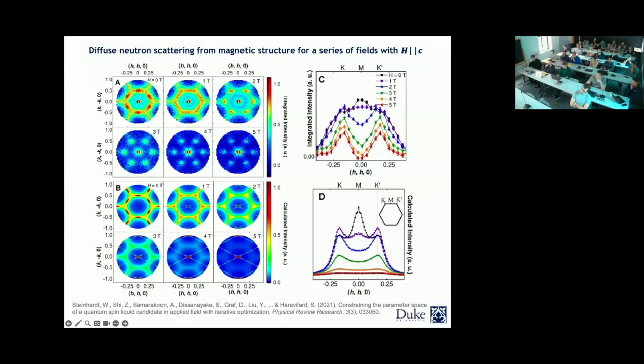Okay. So what we did was that we went up in the field. We were very patient actually. We started to go up in increments of 1 Tesla. At 1 Tesla, we start to see that the intensities at the M point are now more homogeneous. But look what happens at 2 Tesla. At 2 Tesla, the intensity which was at the M point is now shifting to the K points. And when we went even higher in field, above 5 Tesla, it starts to go away. You lose all the excitations and the intensities.